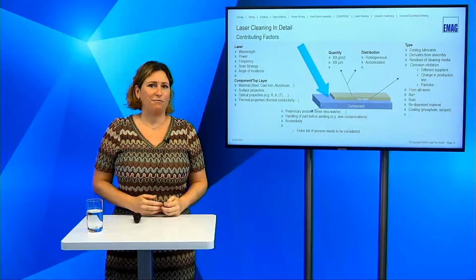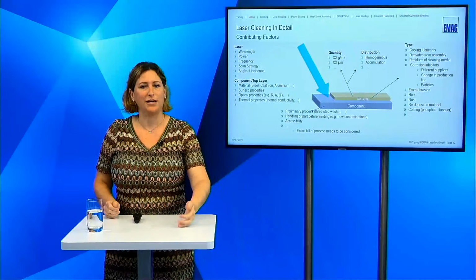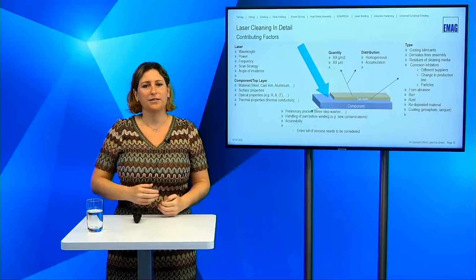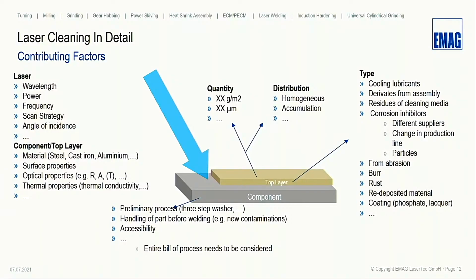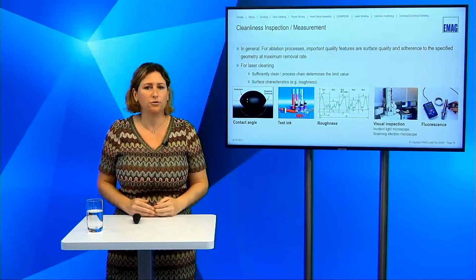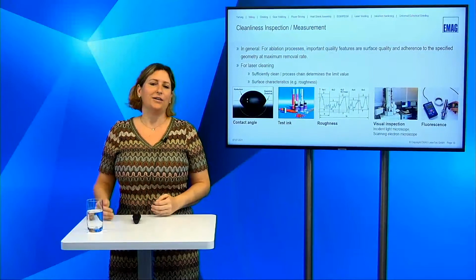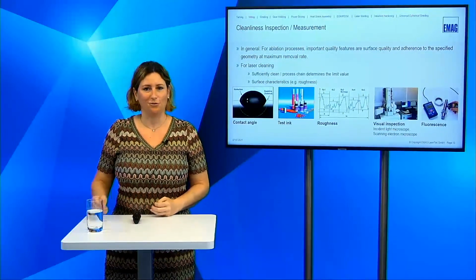Since you have a lot of things to take into account, you have the laser beam. The laser beam has, for example, a certain wavelength. The wavelength will be absorbed differently by the material, if it's steel or ceramics. So you have to take into account the laser parameters. The component has its influence because it has a certain reflectivity and a certain heat diffusion into the material. The top layer you want to remove has an influence too. It could also be reflective or transmitting. The amount of it is also taken into account in the laser process. There are a lot of parameters, but the goal should be to remove your top layer, your contamination, to have a good quality and also a reduced process time.